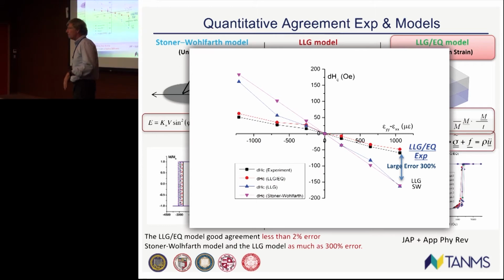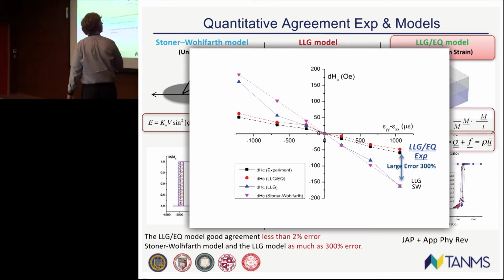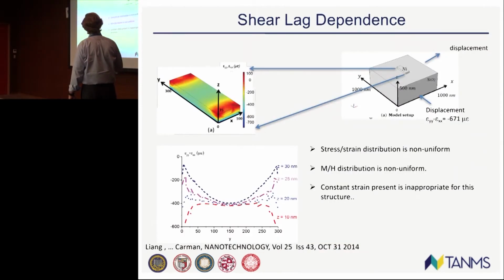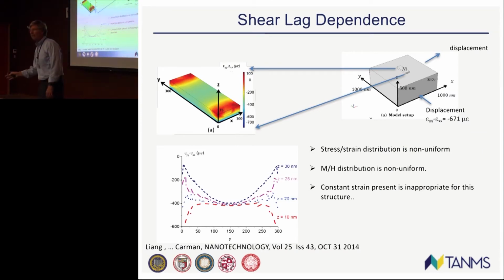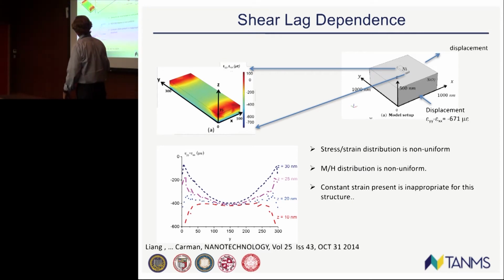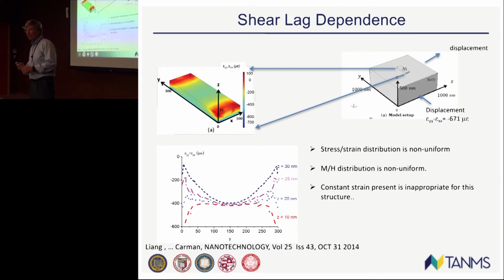It's really simple. If you go and you look at this nickel nanodot here, the first thing you'll see if you look at it from a mechanical perspective, you see these free edges here? The tractions or stresses have to vanish because it's a free edge. So basically here there's no stress, but in the middle you have uniform field. In mechanics, by the way, guys, remember I told you I'm a mechanical engineer, we call that shear lag phenomenon. We've known about that 50 years.